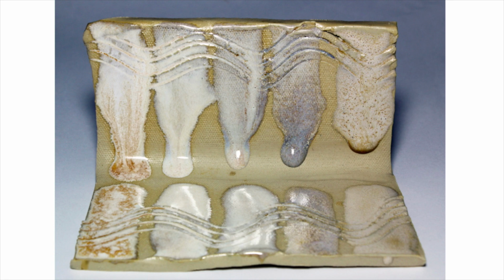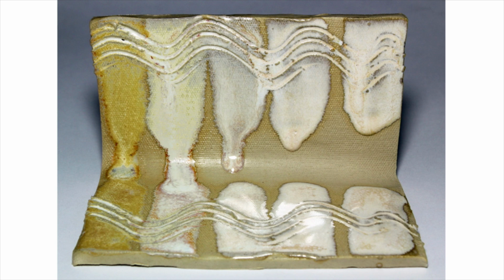Or you can take out all of the silica and add it back in 10 to 15% increments. Note how increasing amounts of silica can also control the flow of the glaze as it raises the melting temperature.